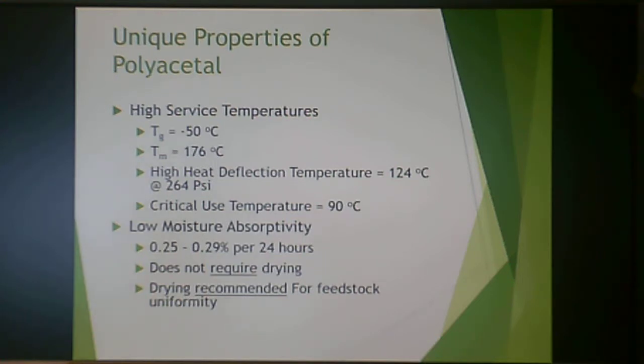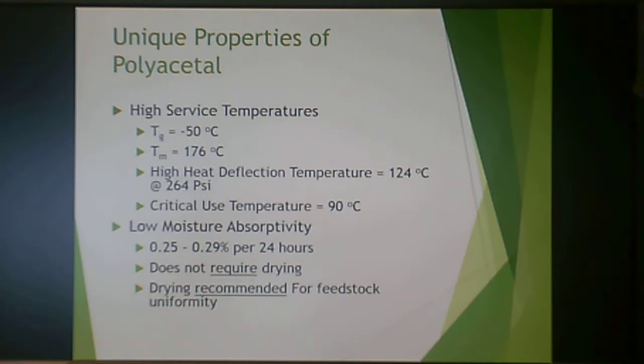Its heat deflection temperature is 124°C and critical use temperature is 90°C. It must be kept below 110°C to prevent catalytic degradation to monomer. Polyacetal has low moisture absorptivity at 0.29% in 24 hours; it does not require drying, but is often dried for feedstock uniformity since people get in the habit of drying engineering thermoplastics.